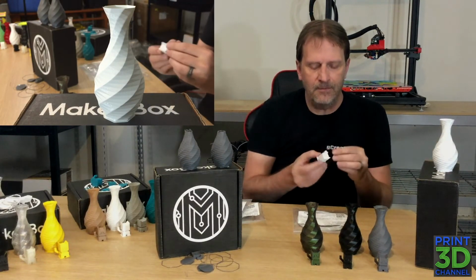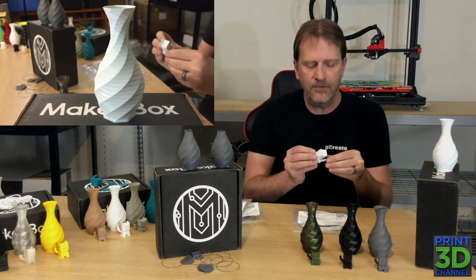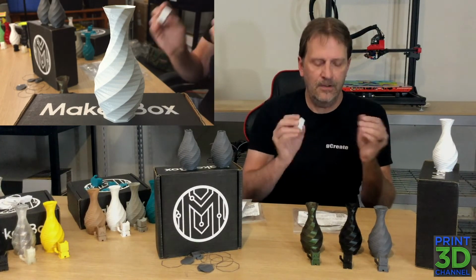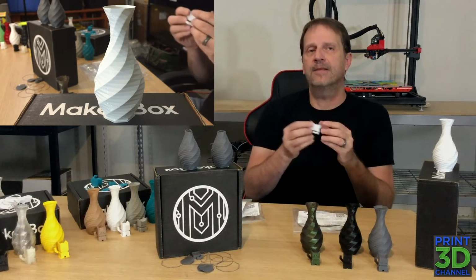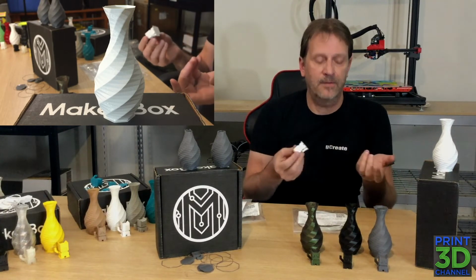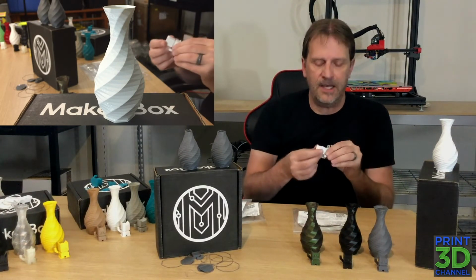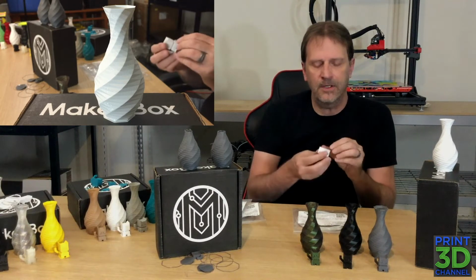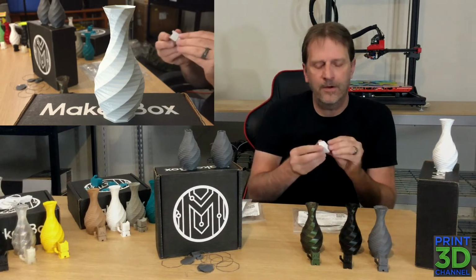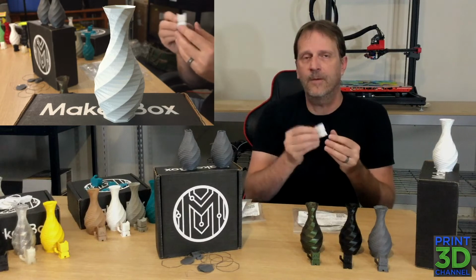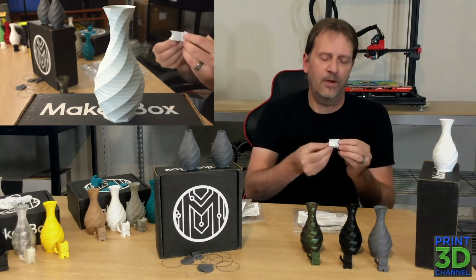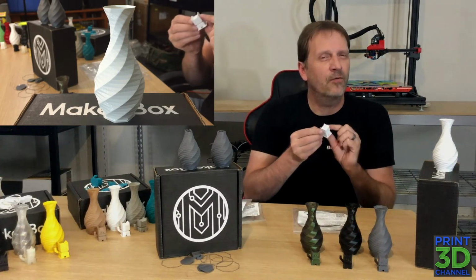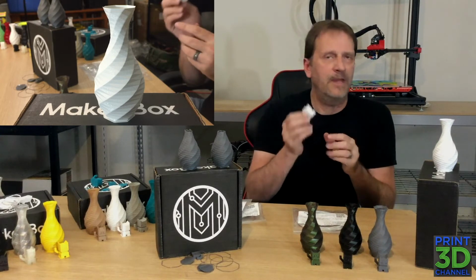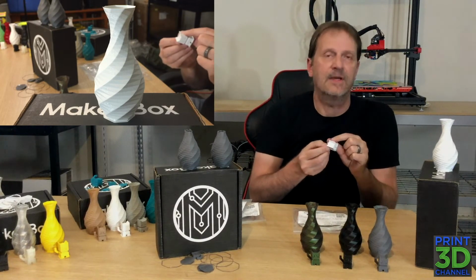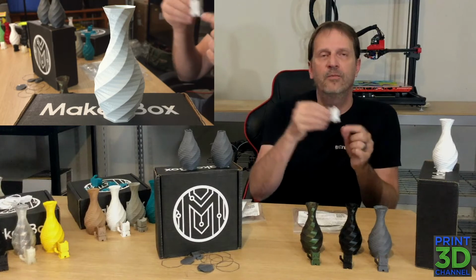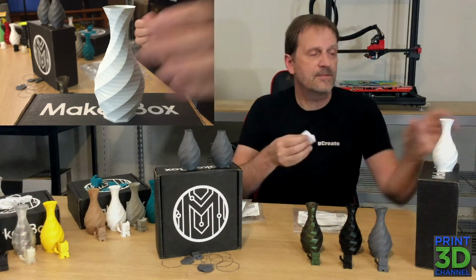The Cali Cat had very minor issues, but it was mostly due to the heat. We're running this at 210. I could have backed this down to 205 or even 200 for PLA, but I decided to keep it at 210. And the Cali Cat actually turned out really good. There is just a little bit of melting in the corners, but this is less than some of the other prints, and I kept the temperature steady where it was. I do see a little bit of over extrusion in some areas. Maybe that's caused by the temperature, so you can see a lot of the layer lines and layer movement lines. But overall, this is really easy to print with.